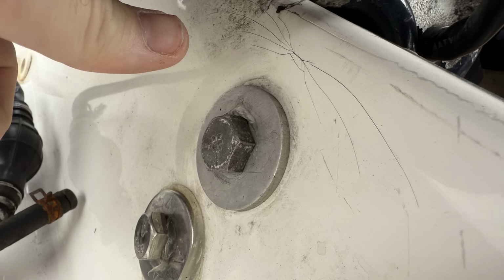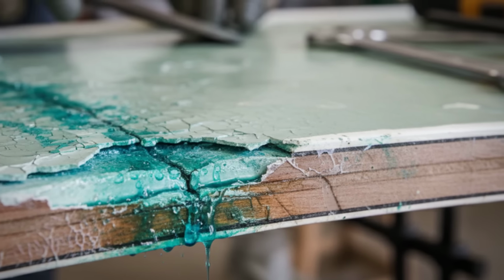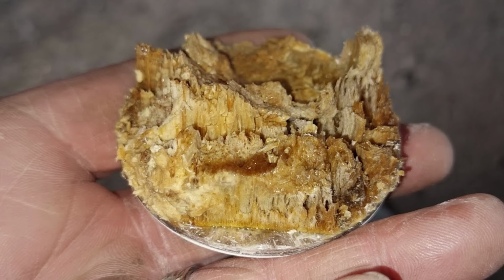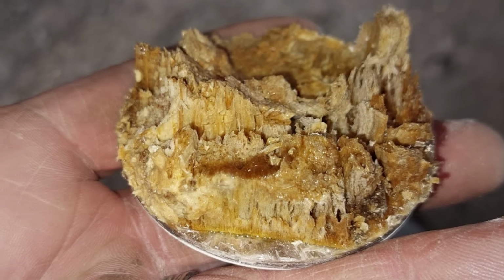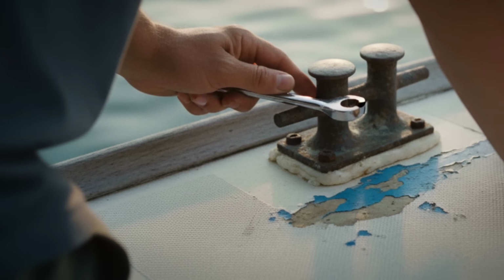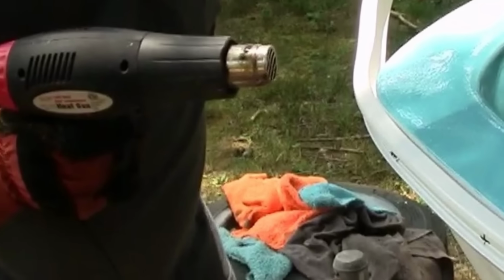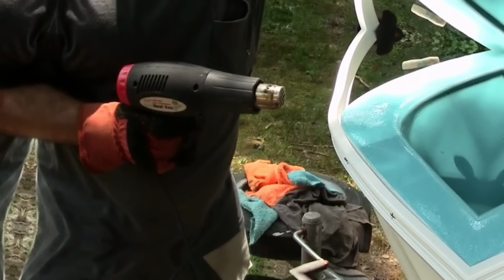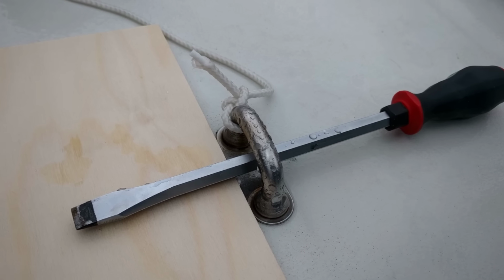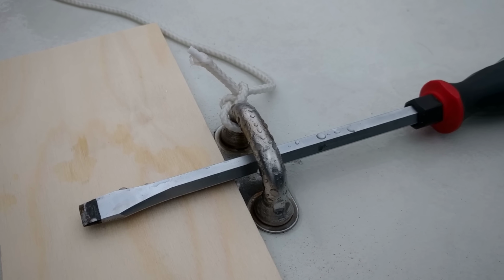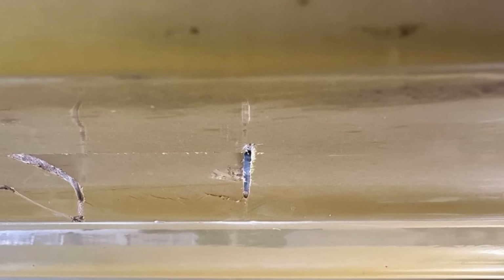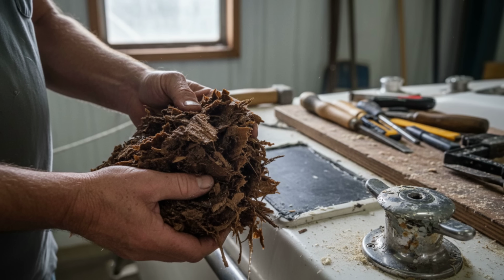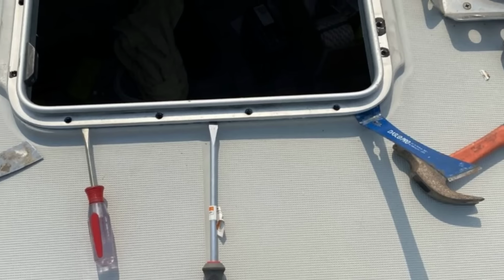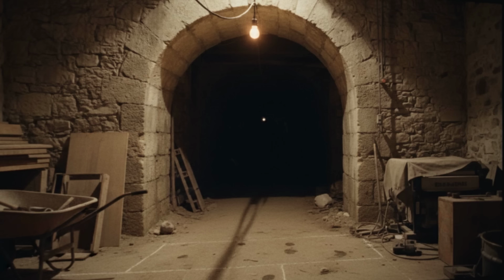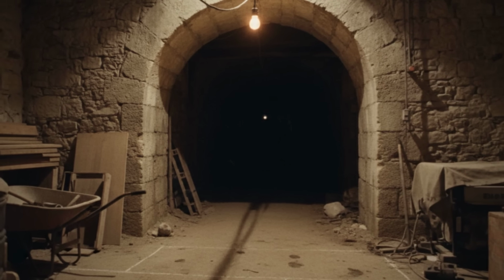Micro cracks radiate out from the bolt holes, spidering through the brittle top layer. Water finds these cracks and starts seeping into the balsa. The core goes soft, loses its grip, and the cycle accelerates. Now comes the moment of truth. The owner grabs a wrench, maybe a heat gun, and tries to pull the hardware. The fitting refuses to budge. He pries harder. The gel coat lifts with a sickening pop, bringing a chunk of laminate and a fistful of rotten balsa with it. What started as a simple rebedding job has turned into a full-scale core repair.